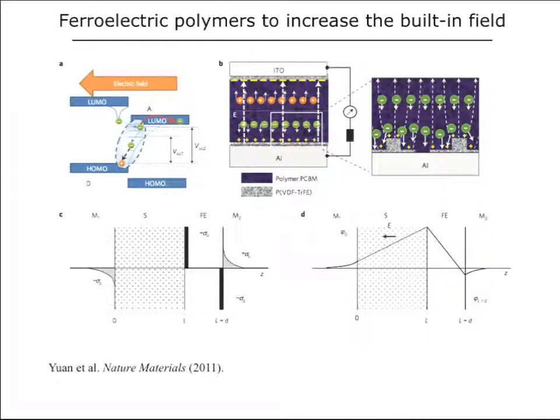I'd like to bring up one little trick that was published recently by Yang Yang's group at UCLA, and I really like this. So what he has done is to intercalate a ferroelectric polymer into the device at one of the electrodes. And by electric repoling the device, this induces a large built-in field into the structure. And the idea is to have a large built-in field that will break up that charge transfer exciton, that CT state, and to hopefully get more current out of the device.